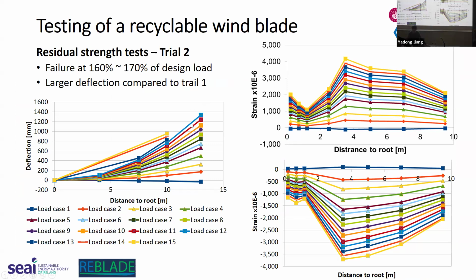So you can see it has a very high deflection. At the last 3 steps, we got out of range of most of the displacement sensors. You can just capture 2 points. All these are out of range, and we have one displacement transducer damaged due to the breaking and the energy release of the blade. And if we compare the strain between this test and the previous static test, we didn't see a lot of changes in the strain, and all these data points are from before the failure. So that's comparable. But if we compare the displacements, we found there is a slight increase in the deflection.